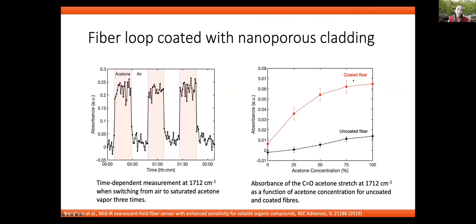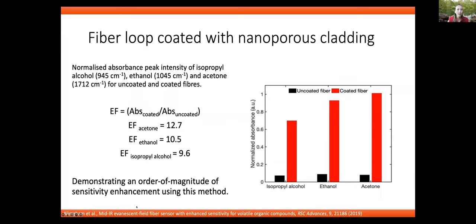And here we have a comparison of the coated fiber and uncoated fiber as a function of acetone concentration. And we can see that we do improve the sensitivity for this. And then we did this for three different VOCs: isopropyl alcohol, ethanol, and acetone. The black bars are for the uncoated fiber, the red is for coated. Also, we can see that the enhancement factor for the improved sensitivity for the different VOCs is different.